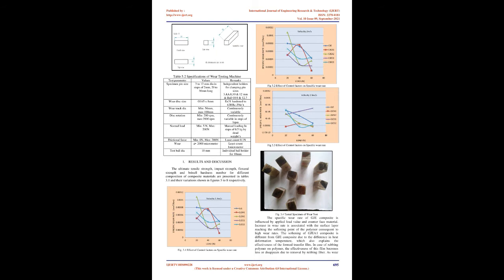Care has been taken that the specimen was continuously cleaned with woolen cloth to avoid the entrapment of wear debris and to achieve a uniform experimental procedure. After each test, the disc was cleaned using acetone solution. The wear testing machine is microprocessor controlled, in which height loss and frictional force can be monitored simultaneously by a PC-based data logging system. The height loss of the pin specimen was measured using a linear variable differential transducer, LVDT, and frictional force was measured using a load cell.